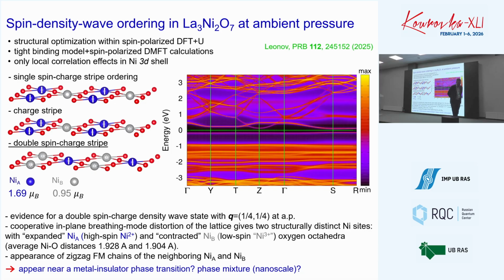Well, this is also a nice question. Can we compute phonons for a material which is close to some kind of localization limit, exactly this intermediate regime? I would say there are some claims that people use density functional, non-magnetic calculation to estimate the electron-phonon interaction strength, and it was too small to reproduce any superconductivity. I would say the estimate was less than 1K. So I see, 0.1K. Experimental wise, is there some isotope effect?